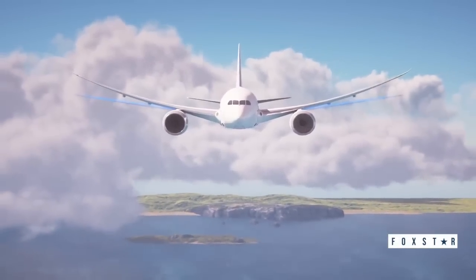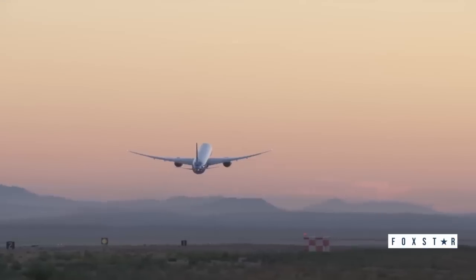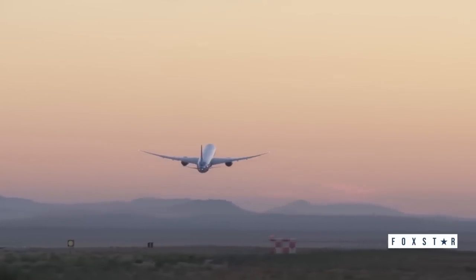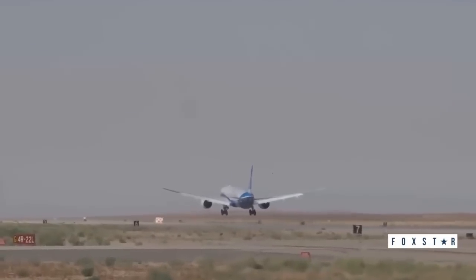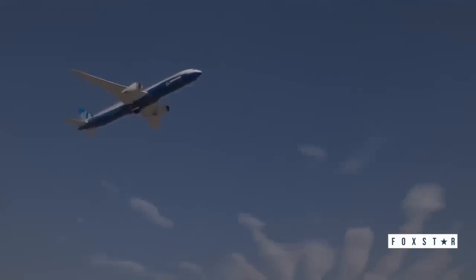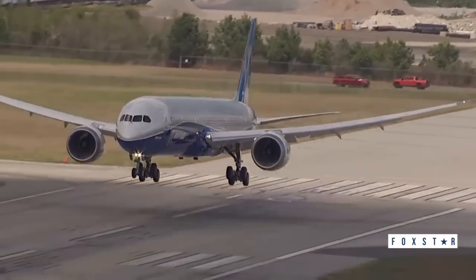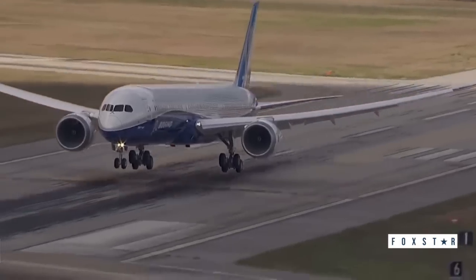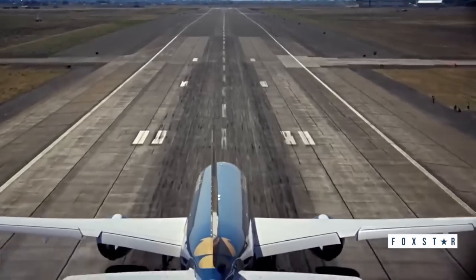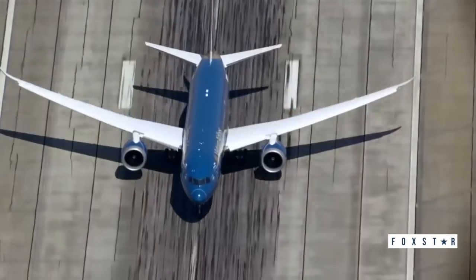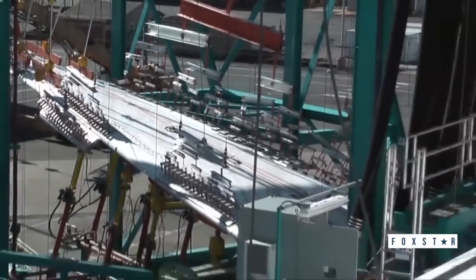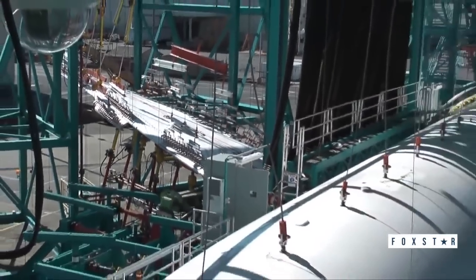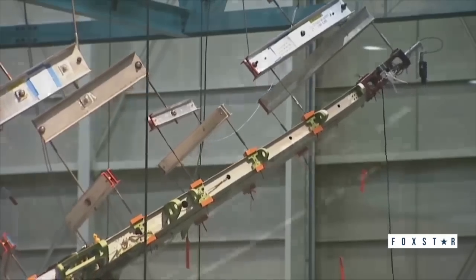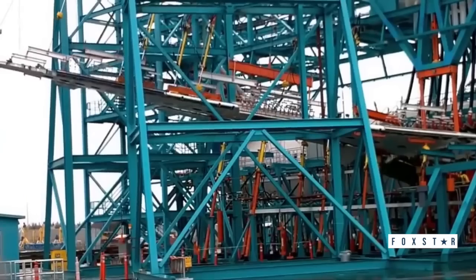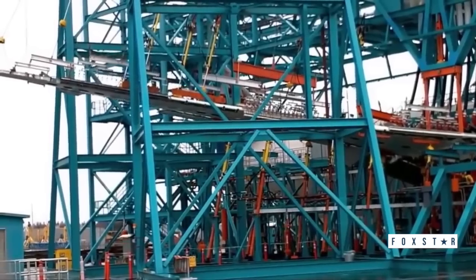That sounds like a lot, but in order to get certified by the FAA, every plane needs to be able to handle 150% of the plane's absolute maximum expected load during flight for 3 seconds. And during that test, the 787's wing bent upwards by 7.6 meters. That's a great deal of bending, despite carbon fiber composites being stiffer than aluminium, meaning it takes more force to deform the same volume of material.